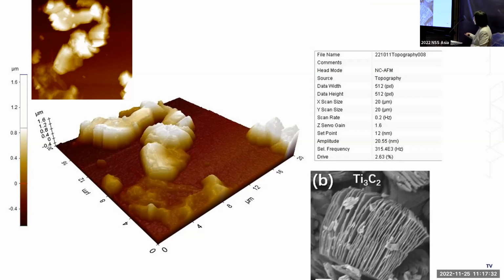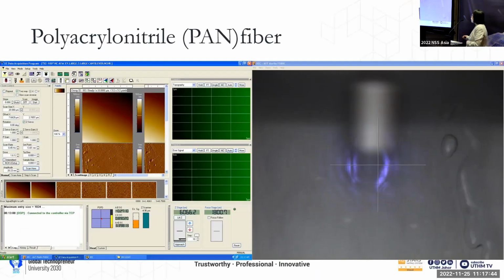So it's kind of interesting, but we have tried a few attempts because it depends on how well the particle is stabilized on the surface. But you see, we are able to determine the thickness of the MXene. Right, so this is something interesting to us, right? Okay, so then we look at if we can apply AFM to polymeric material, polyacrylonitrile, PAN fiber, right? So this is what we get.